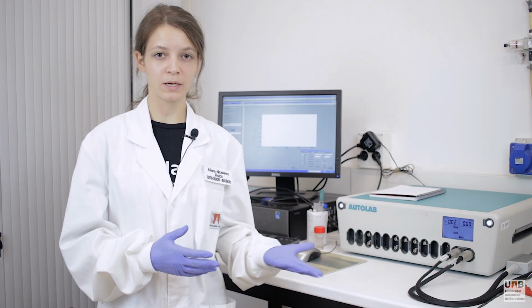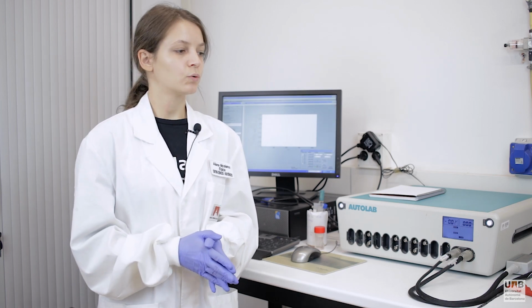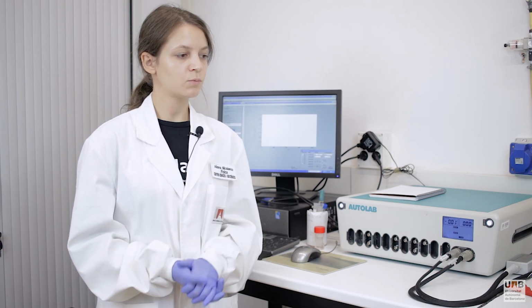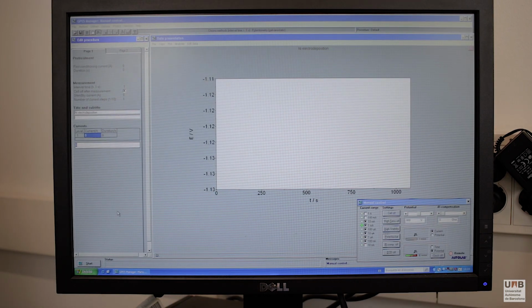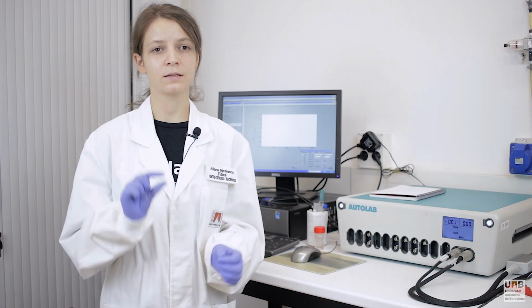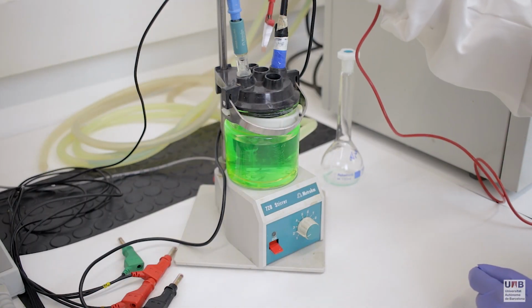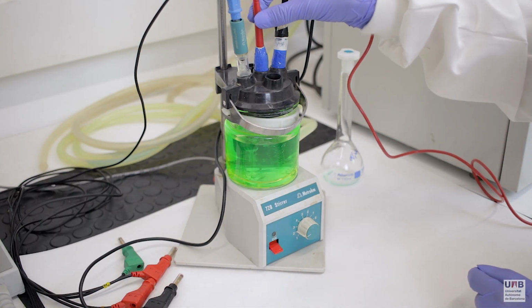Now, when the cell is ready, we are going to define electrodeposition conditions, that is voltage or current that will be applied, and the time. So for the continuous nickel layer, we will do galvanostatic electrodeposition, that is, we will be applying a constant current of 8 milliamps, that corresponds to 40 milliamps per centimeter square, the current density, and we will deposit for 120 seconds. That will give us a thin film of about 600 nanometers thickness. Now we are ready to insert the working electrode and press start.